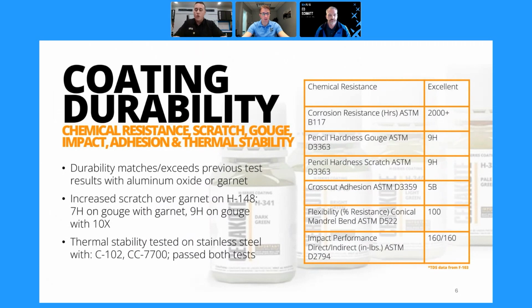And then C102 and C7700 were the main two colors that I used on our thermal testing. We ramped it all the way up to 1800 degrees and then cooled all the way back down to room temperature, and both of them still maintained adhesion, which was really awesome.